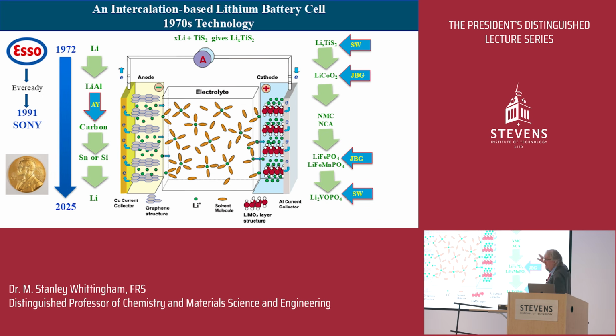But there's a message here. Almost all the battery materials we use are thermodynamically metastable at some state. So if you take this compound, take the lithium out, then warm it up, it will fall apart. And this is one of the dangers of these compounds. They're unstable, so they can release oxygen, and that's the oxygen that can cause fires. Cobalt's too expensive, so nowadays we use a mixture of nickel, manganese, and cobalt, NMC, or Tesla uses nickel, cobalt, and aluminum.